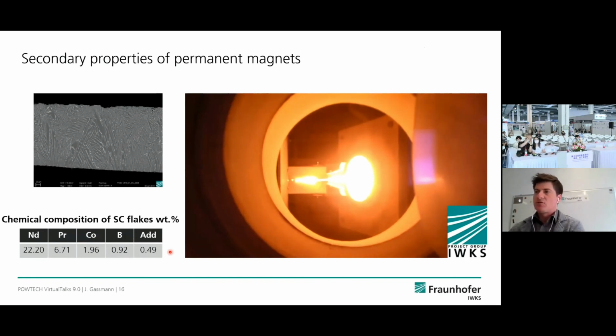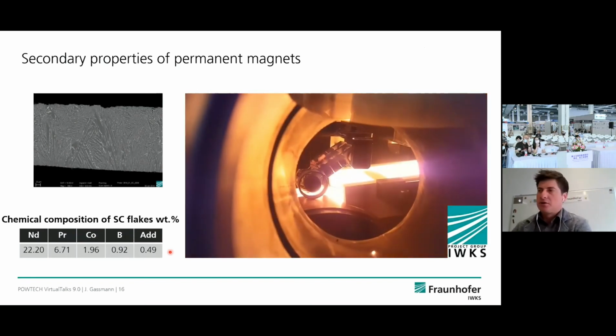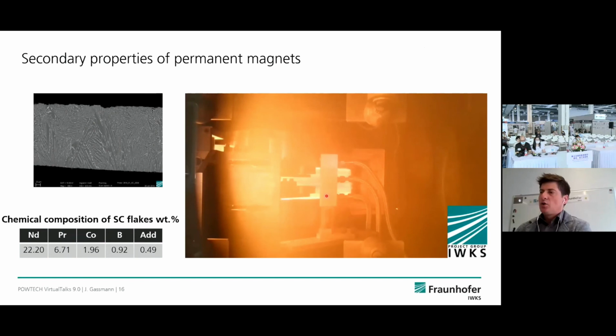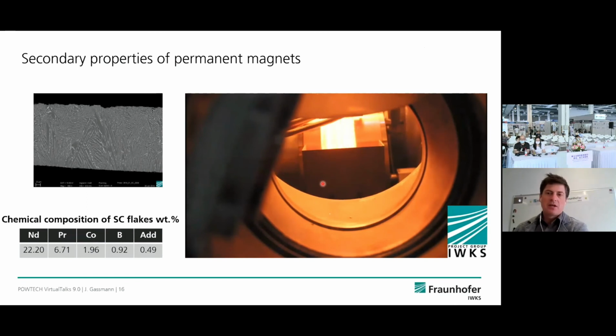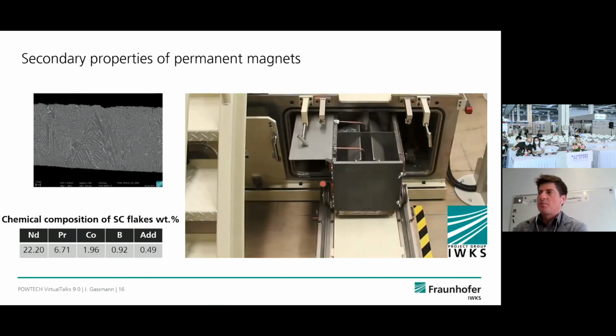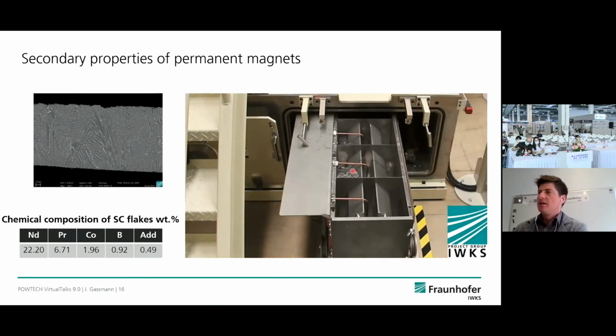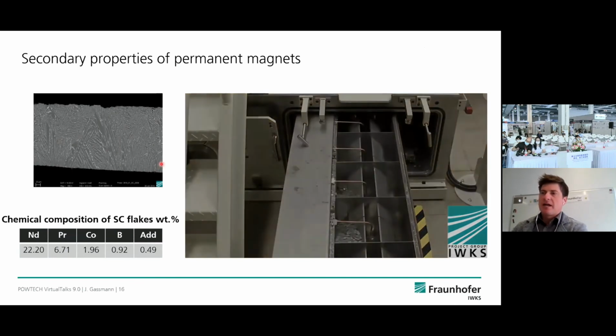So we started with strip casting, which is a state-of-the-art technology for producing permanent magnets. Here's the material. The melt is cooled on a metal-cooled wheel, and flakes are produced with a proper chemical composition and a microstructure which is feasible for producing permanent magnets. So here are the flakes in a collection chamber, and basically this is the microstructure one needs. So one has lamella distances of about 3 to 6 micrometers, and these are rare earth-rich phases which are needed to produce permanent magnets.